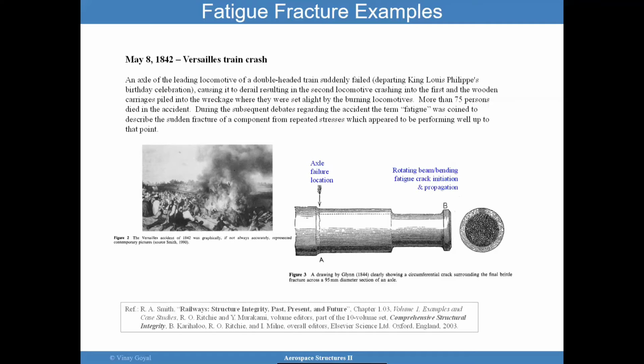So there's no sign of failure until it happened. Now you have the axle here. We know that the axle has to take the weight of the train, and also we know it's rotating. So the axle failed more at a fillet area. And so here you have some sort of rotating beam bending behavior because the beam is rotating. And so you have bending going on. And so then you had the unfortunate situation where the fatigue crack initiated and propagated.